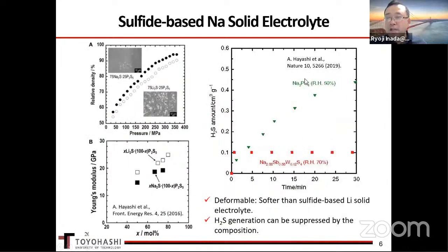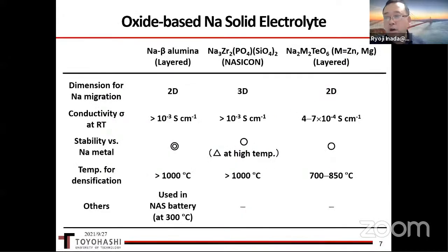Sorry. And similar to the sulfide-based lithium solid electrolyte, sulfide-based sodium solid electrolyte is very easy to deform. The modulus of sodium thiophosphate, as shown in this graph, is slightly smaller than lithium thiophosphate. Most sulfide-based sodium solid electrolytes react with water in air to form toxic hydrogen sulfide gas, as shown here. But this toxic gas formation can be suppressed by controlling the composition of the solid electrolyte materials, as shown in this graph. Okay, next, I'd like to move to the topic of the oxide solid electrolyte.